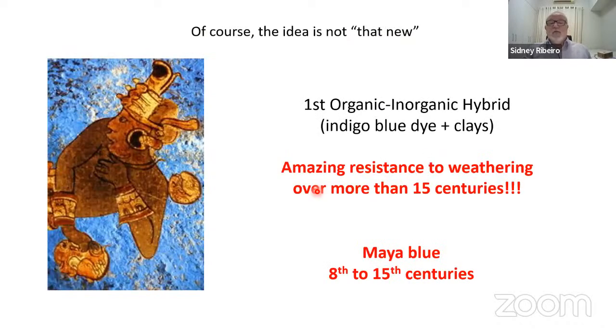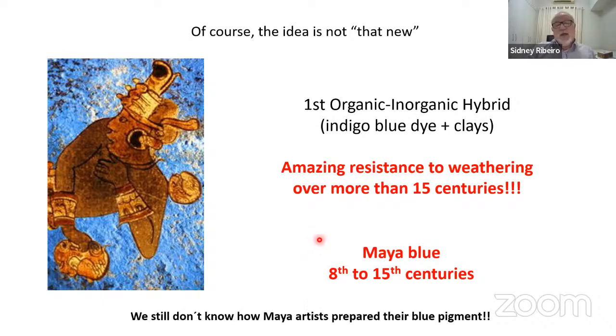Of course, this idea is not new, just to mention that the first organic-inorganic hybrid was made by the Maya. The Mayas in Central America were able to prepare this blue pigment. And this blue pigment is made of an organic dye, indigo blue dye, and clays. And you can still see their blue pigment after some centuries. They are very resistant to weathering for more than 15 centuries. This is amazing. If you take this dye, it will degrade under the sun. And they were able to prepare that, and I must say that we still don't know exactly how they prepared their blue pigment, these first organic-inorganic hybrids.